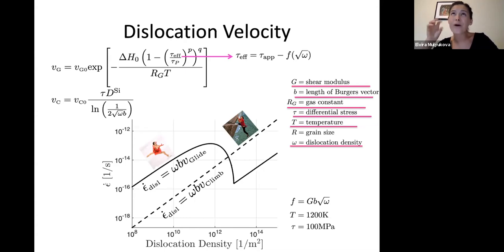So one of the main complications in understanding the physics of dislocations is those long-ranging strain and stresses that the presence of a dislocation induces within the crystal. So the effective stress that is driving the glide is a function of some applied stress minus, or typically the resistive force from the presence of other dislocations. And again, I want you to get used to this omega symbol that will always stand for dislocation density.